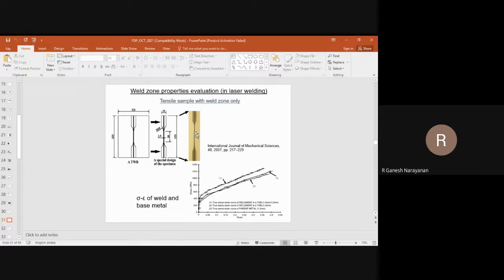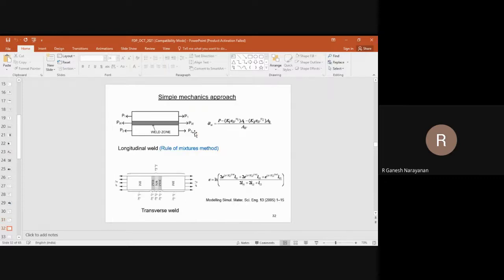There are two different methods. One, you make a tensile sample such that the gauge width is occupied by the entire weld zone only. In this photo you see the sample, only weld zone is available, no base material. Now you clamp it in UTM and then do tensile testing, you will get a stress strain behavior. That is nothing but the stress strain behavior of the weld zone. True stress versus strain I am giving here. But you have to fabricate a sample like this. You have to use wire EDM to cut the sample such that there is no base material combination. There are other methods also.